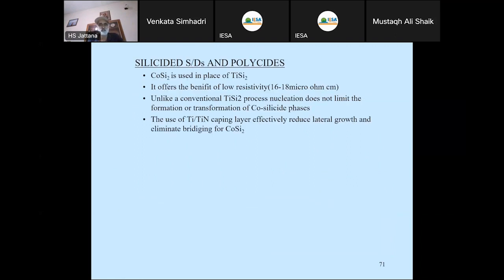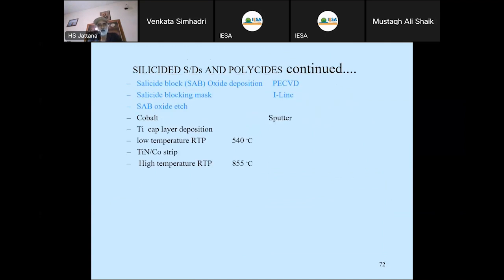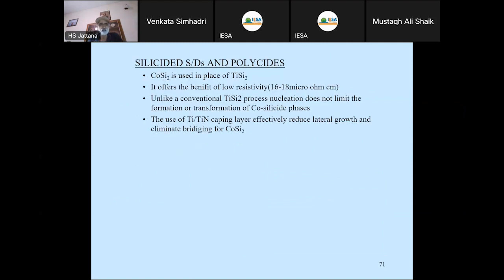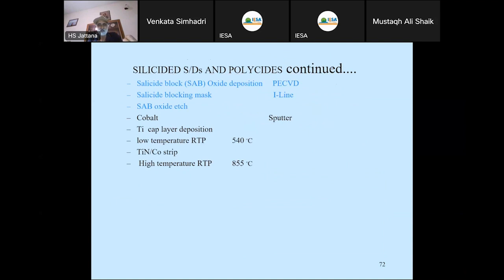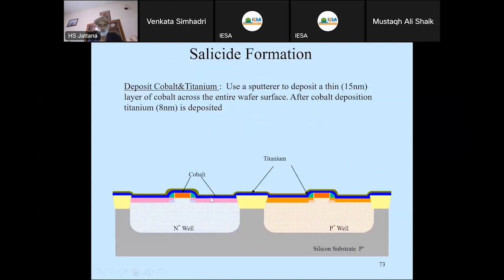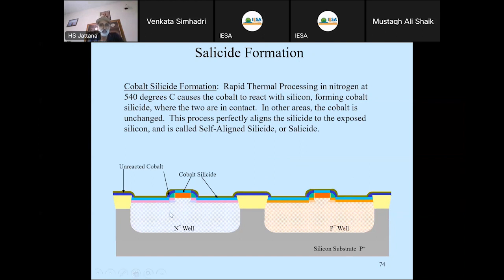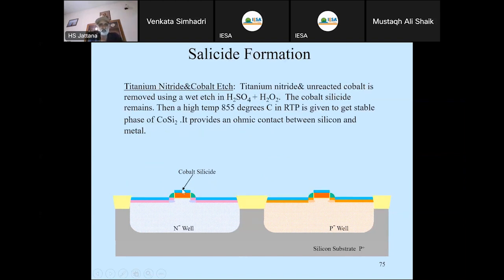We have done the source drain, we have done the contacts, and then contacts on the silicon, we cannot put directly aluminium or things like that. So we have to reduce the contact resistance. So normally a silicide is used, a cobalt or a titanium silicide. We were using cobalt. So we will put a cobalt here. On top of it you can see cobalt is put, and then cobalt will react with silicon to make CoSi2, what is known as cobalt silicide. It's a very thin layer, a few nanometer layer of cobalt is put, and then you can see cobalt silicide will form, and on top of here also cobalt silicide is formed.